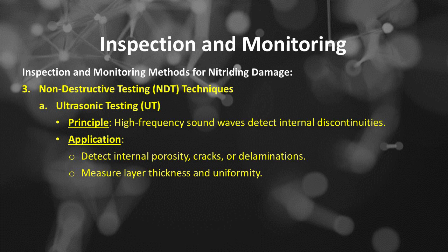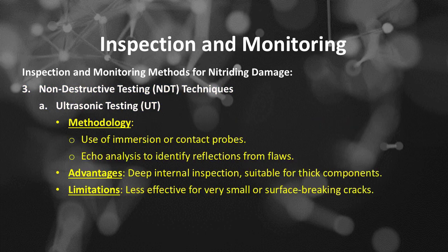Another NDT technique is ultrasonic testing, or UT. The principle of UT is that high-frequency sound waves detect internal discontinuities. The application of the UT technique is to detect internal porosity, cracks, or delaminations, and measure layer thickness and uniformity. The methodology of UT uses immersion or contact probes, with echo analysis to identify reflections from flaws.